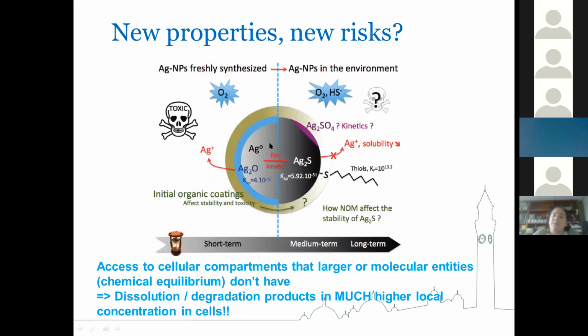And if that happens, taking again the example of silver, silver ions are often considered to be more toxic than silver nanoparticles. But one of the problems that can arise is if an organism or a cell takes up the silver as a particle, and then once internalized, it degrades or dissolves, you will end up with a much higher local concentration in the cells than you would have achieved by equilibrium. So it goes in as a particle and then dissolves, so you get much more in. And that's been called a Trojan horse effect, where the particle form carries in much higher concentrations than would have gone in through chemical equilibrium.